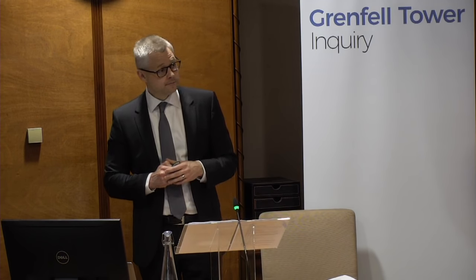And consequently, the burning region becomes larger, producing flammable pyrolysis products at an increasing rate. This can be seen in my video in a moment, as the bottom of the match you'll see is still burning as the top ignites. The flame becomes larger and thereby increases the height of the heated material, which further increases the burning area. This positive feedback loop results in a self-accelerating process and rapid upward spread of flame. The sequence of events is shown in this short video.